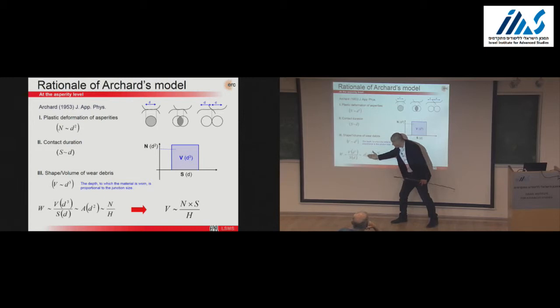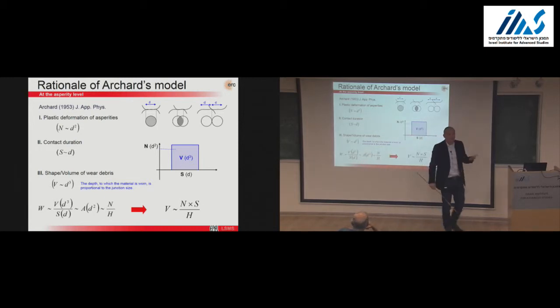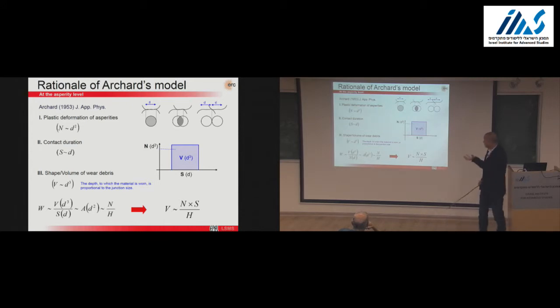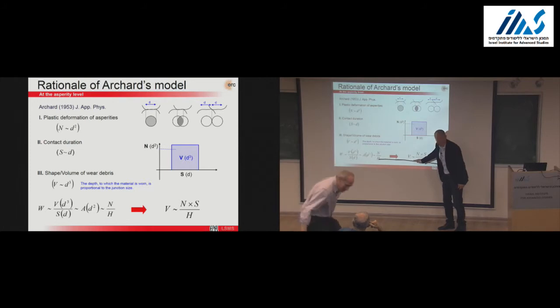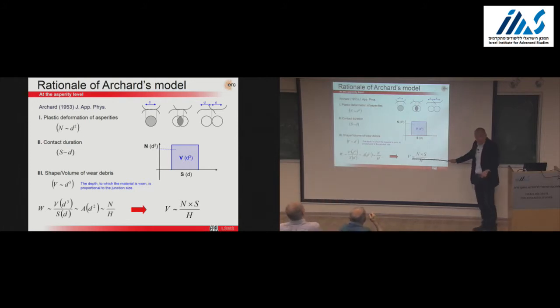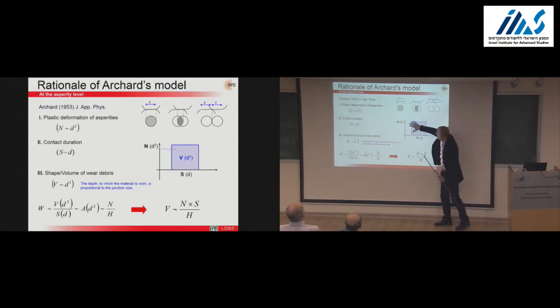So the wear rate should scale with the junction area, A, which is d squared. And this junction area, if you have plastic flow, is really the normal force over the hardness. So you simply get that the wear volume is N times S divided by H. That's the evolution of the normal force as a function of time or sliding distance portrayed in this Archard paper.